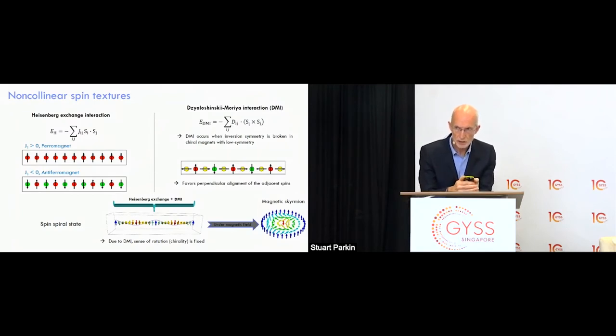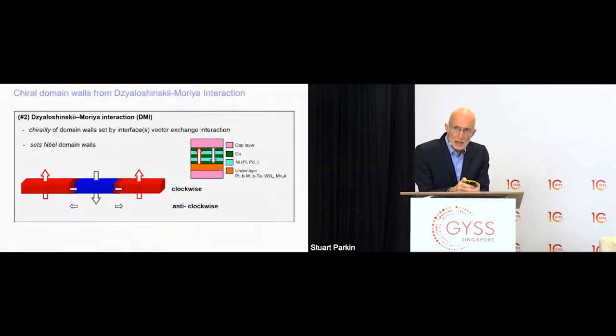However, as I said, there are some materials where the symmetry is broken, no longer centrosymmetric, where with strong spin orbit coupling, this leads to the magnetic moments wanting to be not parallel, as in a ferromagnet, or antiparallel, as in an antiferromagnet, but being perpendicular to one another in a helical or chiral fashion. And this then leads to, for example, as shown in the bottom, spin spiral states in some materials, and if there's time to discuss, skyrmionic objects like this. But in the domain walls I've shown, it leads to the fact that they have a chiral Néel structure. And this is shown here. This is the very important point that the domain walls in this system are not only very narrow, they're only a few nanometers wide, but they also have this chiral structure.